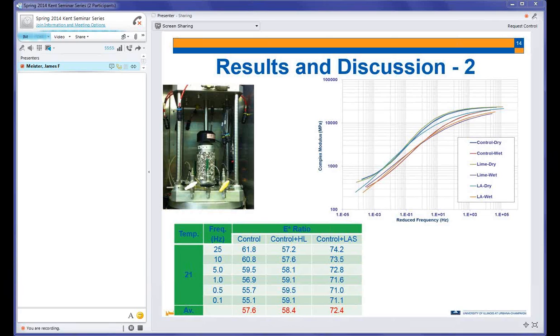So ranking-wise, moisture sensitivity-wise, the liquid anti-strip performed the best here and also in the Lottman test. But the ranking is different for these two, and this could be because of the mechanism. Here we apply only pure compressive stress. For the Lottman, we apply compressive, but we look at the tensile. So this could be the difference. But again, we're not looking at this. We want to compare the push-pull and the Lottman. But since we tested, it was worth looking at the values from this test.